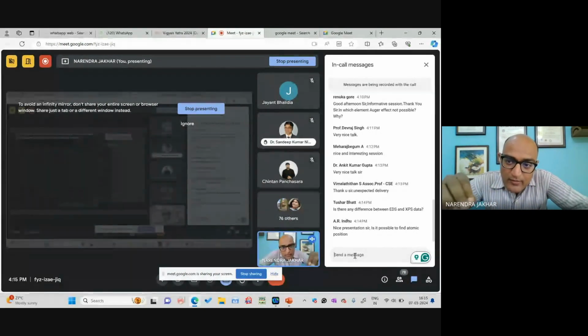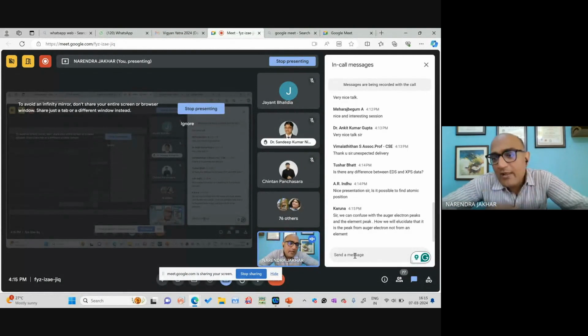Tushar Bhatt, yes, there are many differences between EDS and XPS. EDS is energy dispersive spectroscopy. Usually it is done with TEM and SEM, because in TEM and SEM what you are using is electrons. These electrons eject other electrons, and photons come out from the sample surface. Those are analyzed by the detectors, and this is known as EDS. It will provide us the elemental information, but it will not provide the chemical states of the elements present in the sample. But XPS can also provide us the definite chemical states and the electronic structures.